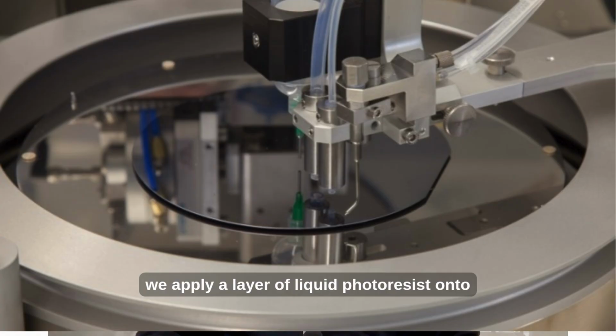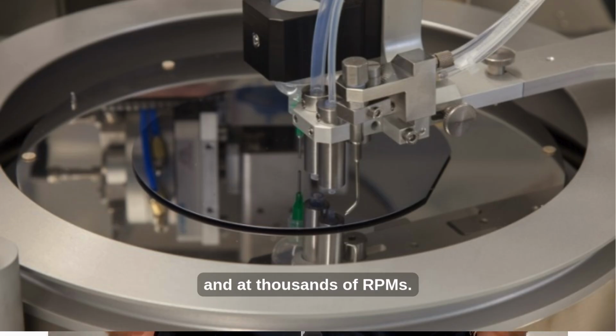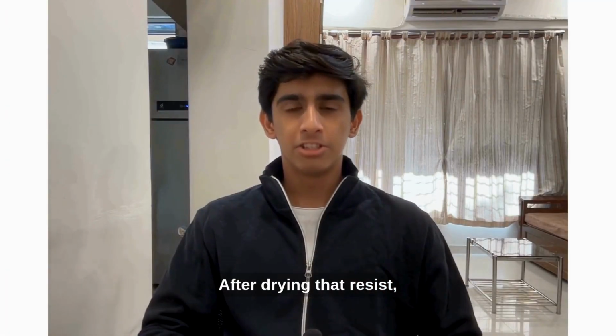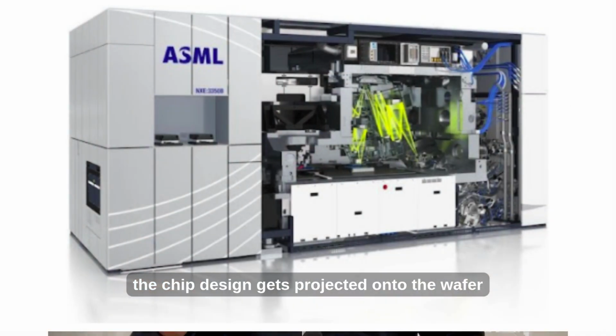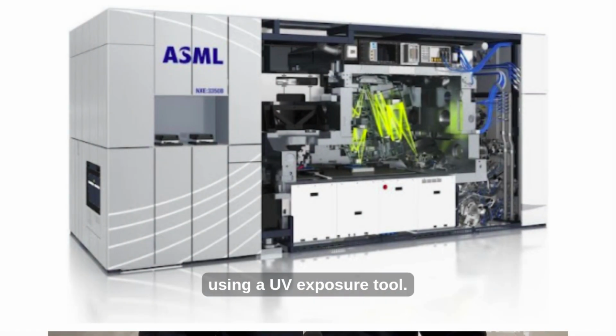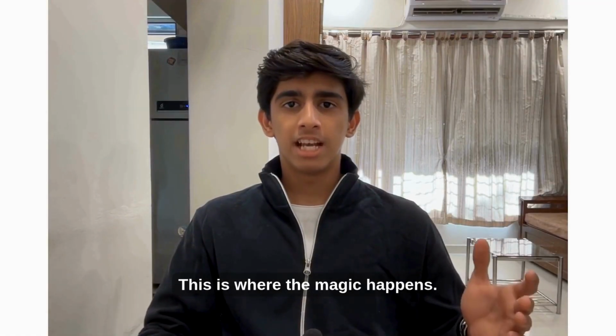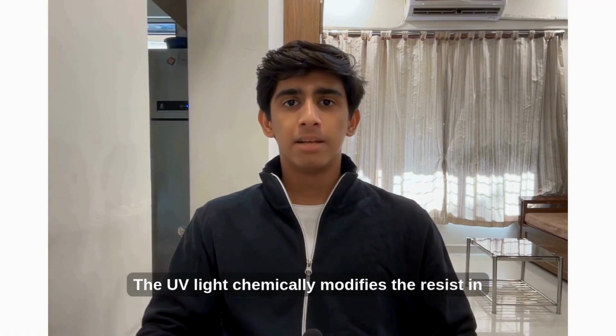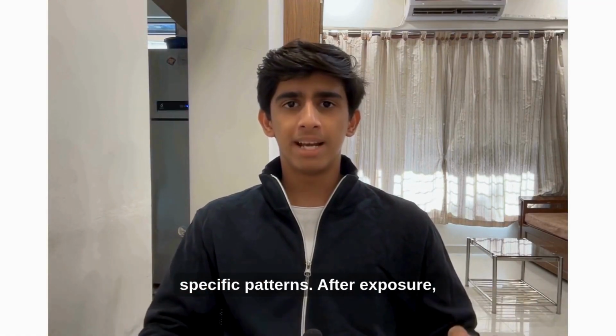Here's how the process works. First, we apply a layer of liquid photoresist onto the wafer using a method called spin coating. Imagine putting honey on a spinning record. That's essentially what's happening, except with incredibly precise chemicals and at thousands of RPMs. After drying that resist layer, the chip design gets projected onto the wafer using a UV exposure tool. This is where the magic happens. The UV light chemically modifies the resist in specific patterns.